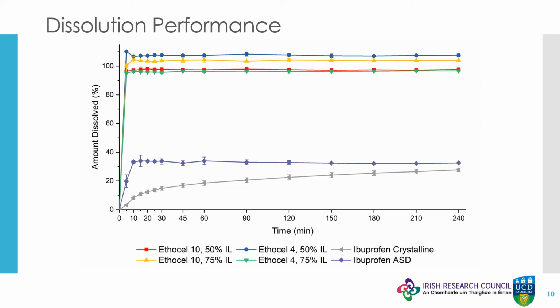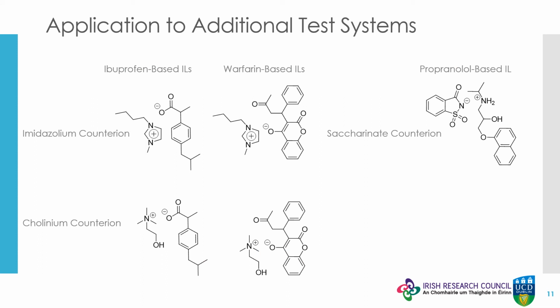Additionally, ASDs require a high ratio of polymer to API to prevent recrystallization of the drug or amorphous phase separation, and so limits the amount of API that can be feasibly incorporated into a solid dosage form. This has largely been addressed by the IL approach outlined here, and shows the potential of this integrated purification approach by enabling significant new possibilities in engineering API forms. The number of ionic liquids that can potentially be formed has been estimated to be higher than 10 to the power of 14, and so there is a huge amount of scope for developing API-derived ILs.